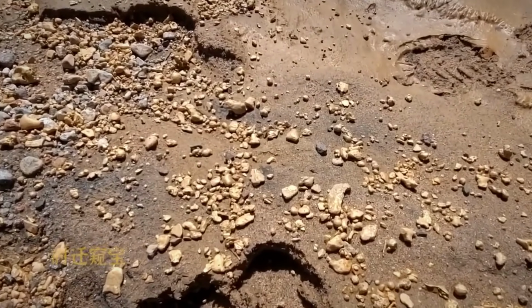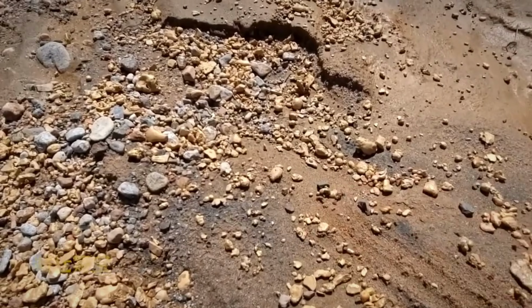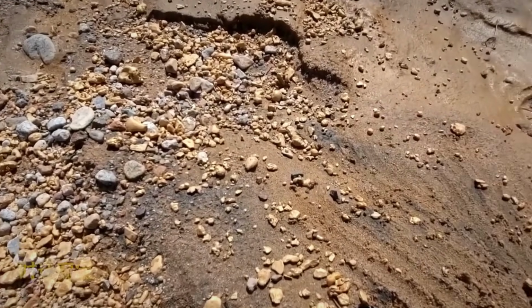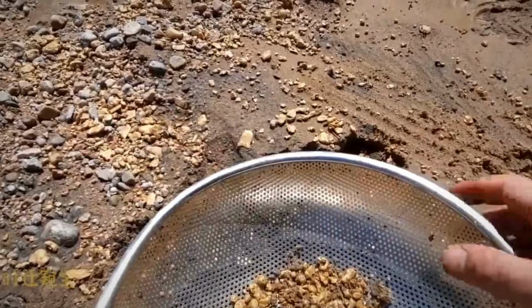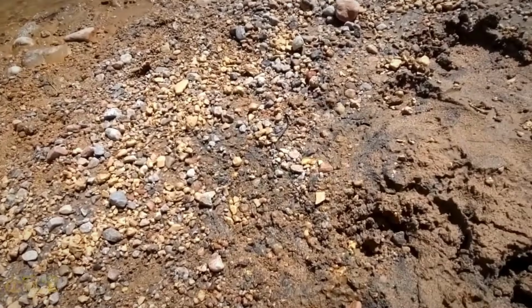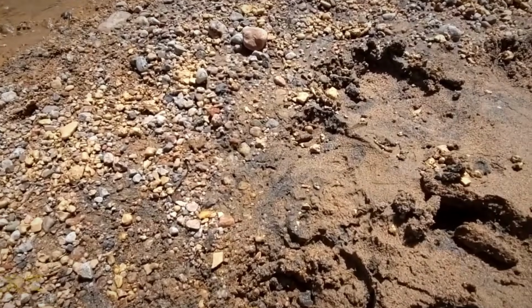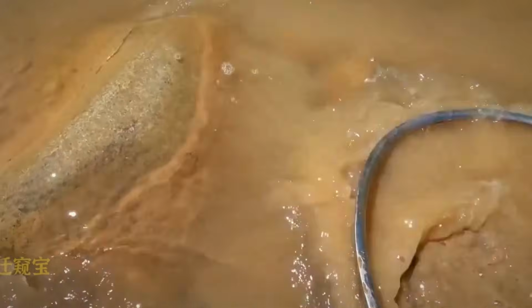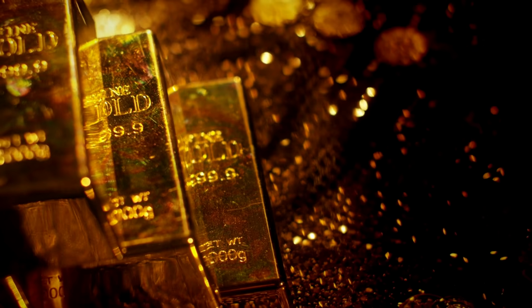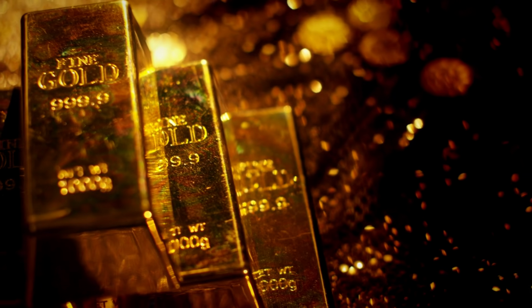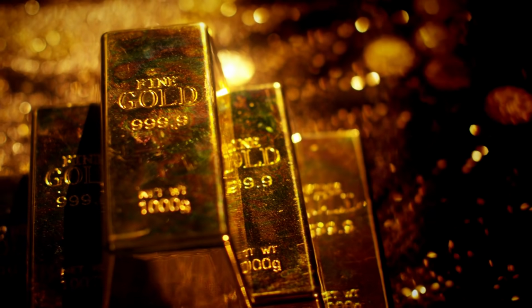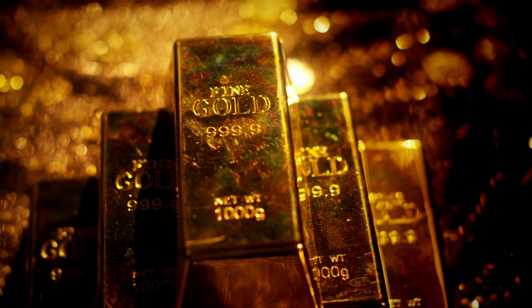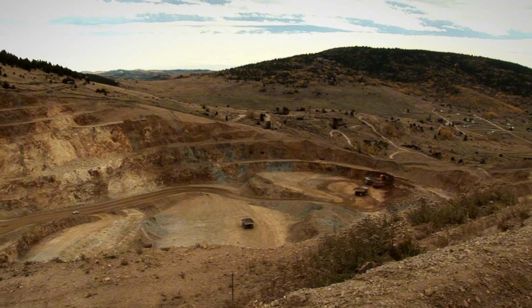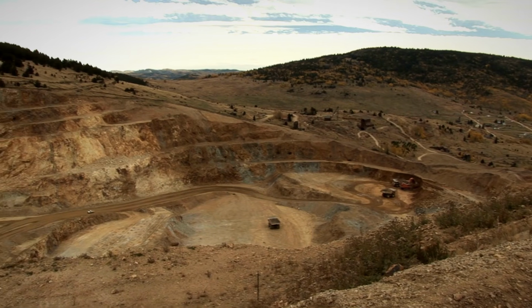Old adits and trenches also reveal key structural clues. Exposed quartz veins, especially those with visible iron staining or sulfide streaks, may still be mineralized. Early miners often stopped work when grades dropped below a few ounces per ton, unaware that modern recovery could profitably extract much lower concentrations. Additionally, veins that pinch out on the surface may widen or enrich at depth, a common phenomenon in orogenic gold systems.